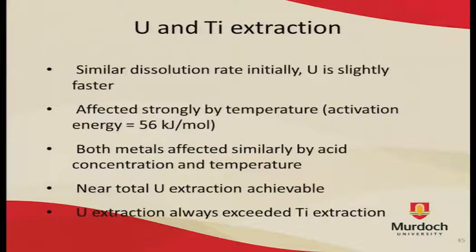Varying the acid concentration had a similar effect on both as well. When I looked into the actual effect of the acidity on the reaction rate, it came out with similar coefficients for both metals. Under the harshest set of conditions I used, about 90% of the uranium was extracted within the first half hour. Uranium extraction was higher than titanium extraction in every one of these experiments, but the higher the acid concentration was, the more the titanium extraction approached that of the uranium extraction in the end.